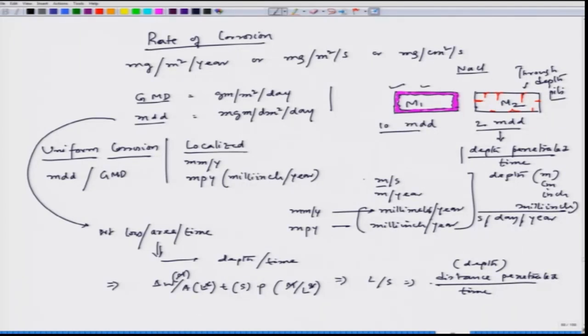Now, one example we can cite, that is, you have also seen it. We have shown one stainless steel plate. You might have noticed that stainless steel plates have got a lot of pits, and those are through pits, and the surface looks absolutely fine, not much corrosion product, but it has got perforated because of the corrosion attack, localized corrosion attack. In that case it is better to express the corrosion rate in the form of depth penetrated or the distance penetrated into the material by time.